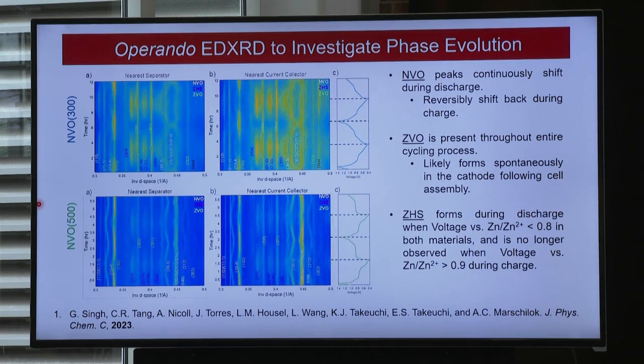With the 300 degree material, we're accessing much more of the active material and the active battery. So we're getting much more complete utilization. And with the porous electrodes that we designed, the reactivity throughout the electrode was fairly uniform. So this was more a material issue than an electrode issue. I will point out that the non-annealed material, and this is a study that we have ongoing now, just begins to dissolve. So it's amorphous enough that it starts to dissolve in the electrolyte, and that contributes to the fade that we're seeing.